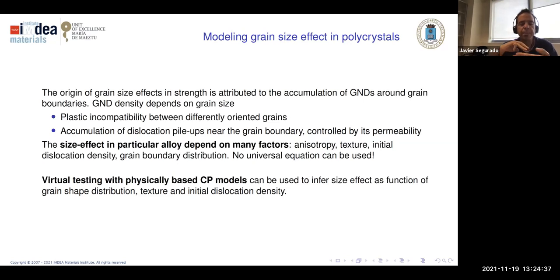So when dislocations slip, they find the grain boundary and they pile up there. They form a pile-up, and this increases strength. The size effect that this piling up forms depends not only on the grain size, but on things like the lattice itself, the anisotropy, the texture, and the initial dislocation density. So just putting in a universal law like Hall-Petch is a very, very strong simplification. So the idea is, don't use just Hall-Petch. Let's try to obtain the relation from virtual testing, and this is what we are going to do.